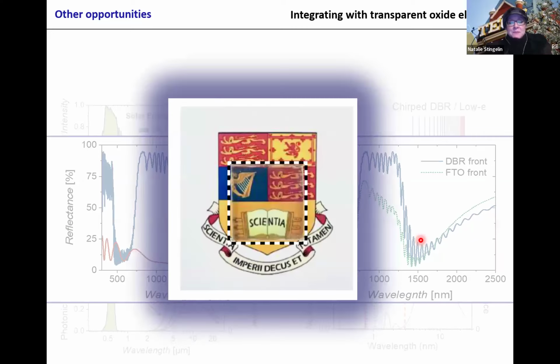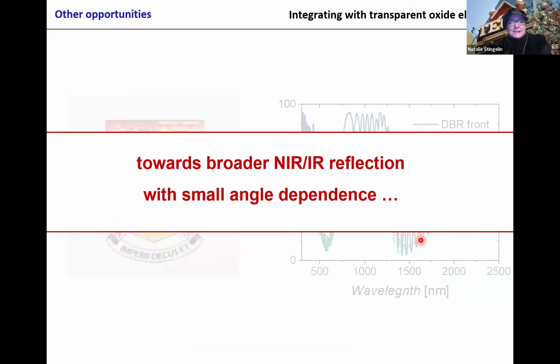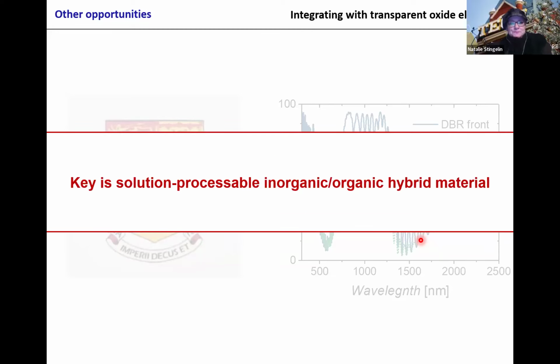And again, you keep the transparency, contrary to a lot of the e-glasses that are used nowadays. So we really could show that we can get a broad near infrared reflection, and importantly, with a small angle dependence.